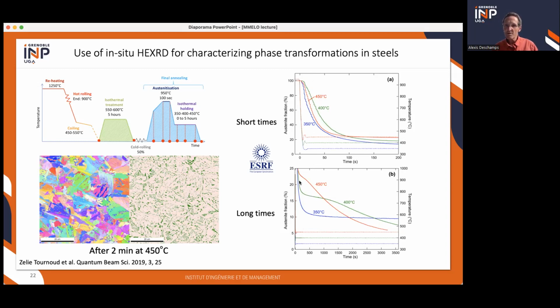So at lower austenite fractions and longer times, then you have a crossover between the 3 temperatures. Namely, at low temperature, you have an almost complete transformation, but the residual austenite is very stable. At 450, it's the contrary. You have a stasis at a higher fraction, and then you have a destabilization of the remaining austenite during time.